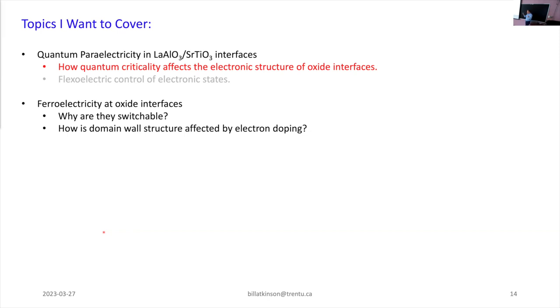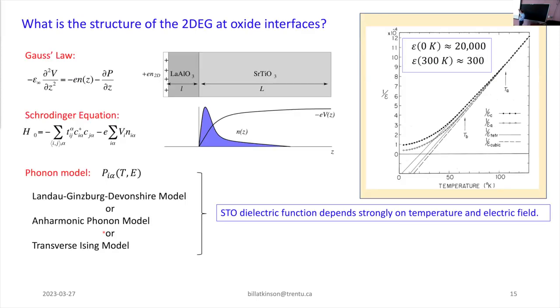So this brings me to the first part of my talk, which is just trying to understand how this quantum paraelectricity affects the structure of the interface. And I need a model for this. Always through this talk, I'm thinking about this cartoon here. And I'm solving, in this case, a discrete grid model where I'm trying to get properties as a function of position in the substrate. I'm assuming translational invariance parallel to the interface, so this really becomes a 1D problem. I have to solve Gauss's law to get the electrostatic potential. The electrostatic potential comes from this surface charge on the LAO plus whatever gate voltages I apply. But it also depends on the electron density in the substrate, and it depends on the polarization in the substrate.